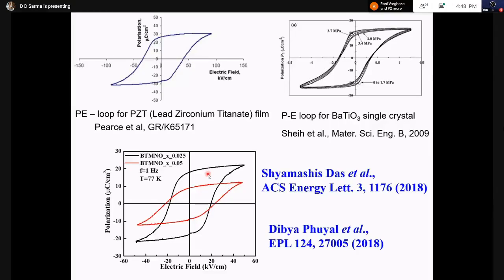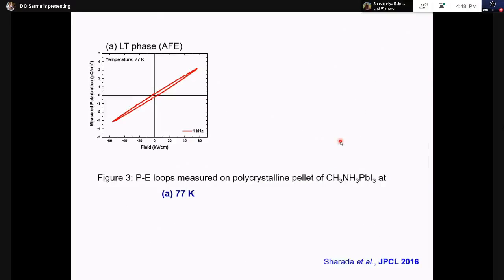These are ferroelectric, and the reason we were excited about it is because we showed that you can lower the band gap almost down to the optimal band gap region below 2 electron volts by making barium titanate doped with some manganese and niobium. But for the purpose of today, I'm showing you that as long as you have a ferroelectric, you have this beautiful ferroelectric loop. Now let's apply this technique to our material.